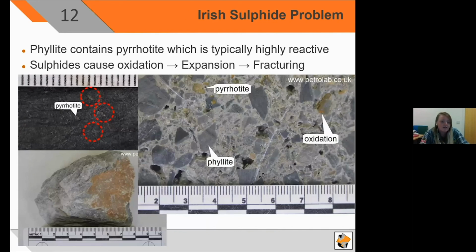So I would say another parallel which can be drawn is sulfide in some of the aggregates from Donegal. So here we have phyllite, which contains pyrrhotite, which is typically highly reactive. You can clearly see here in hand specimen, there's photos of pyrrhotite. In the top left, you've got the abundant elongate lenses parallel to foliation. In the right high mag image there, you've got coarse liberated pyrrhotite derived from the phyllite in the binder. And in the bottom left, you have the actual phyllite rock with the brown smeared oxidation stain, which is, again, common weathering for phyllite.